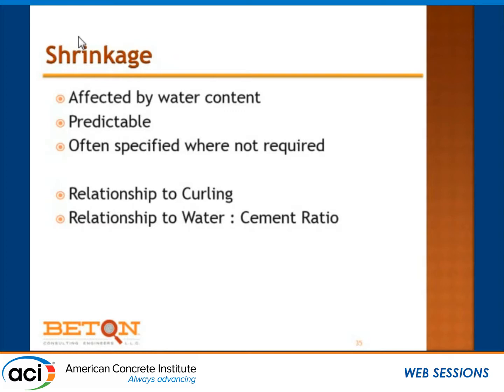Mixes that have a water content below 250 pounds per cubic yard will have moderate to low shrinkage. Below 225, it will have low shrinkage. Above 250 to 300, it's marginal. Anything over 300, shrinkage is probably 0.08, measured by C157. It doesn't matter what aggregates you use, it doesn't matter anything else, because it has to do with where the water is and how much extra water you had relative to the cement.